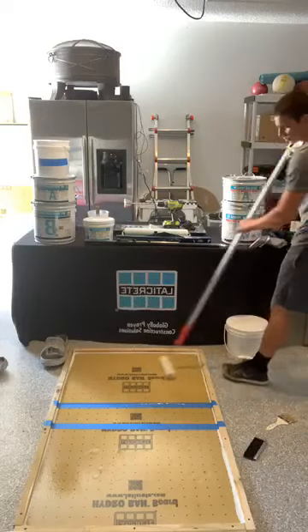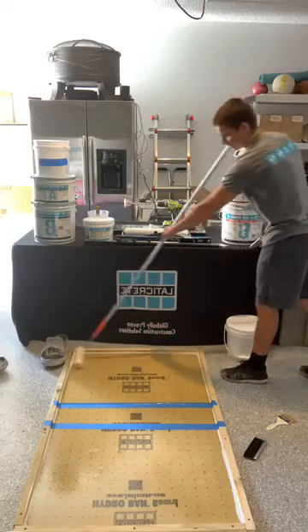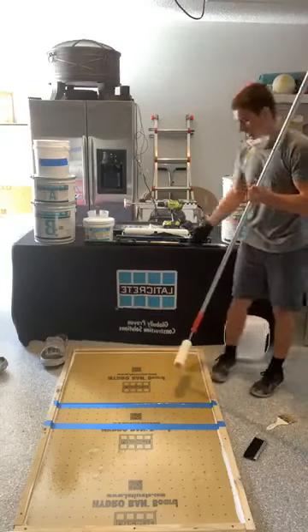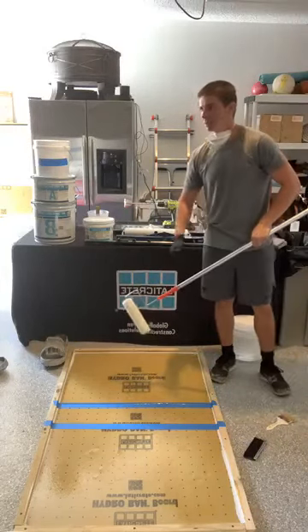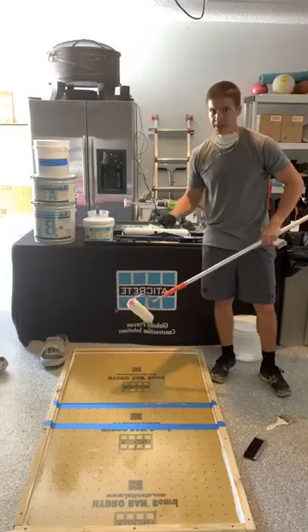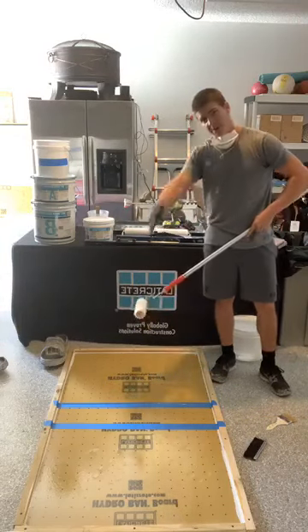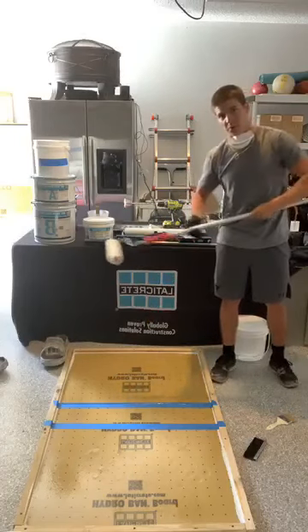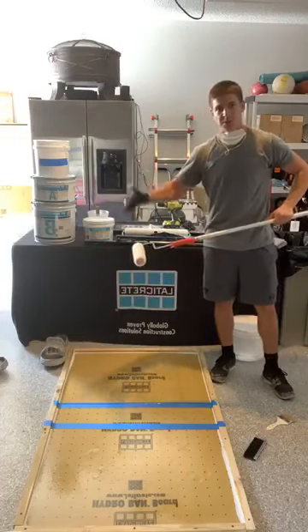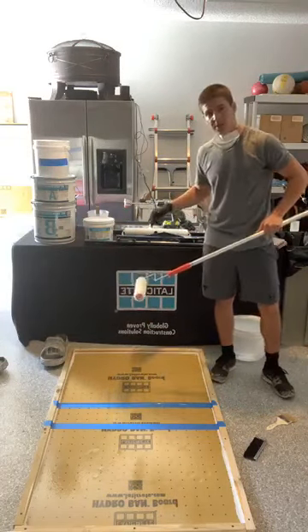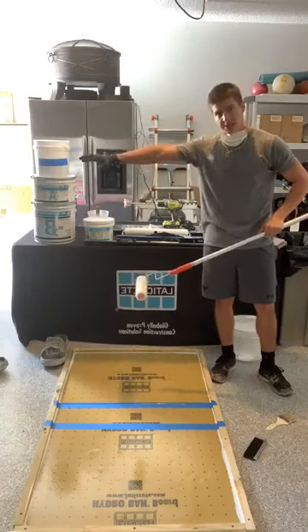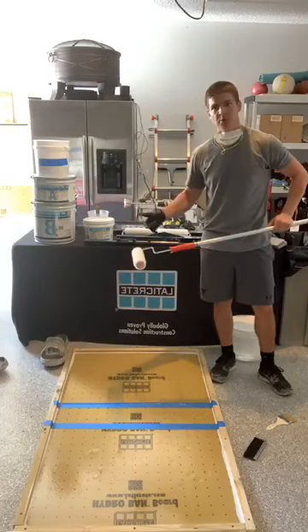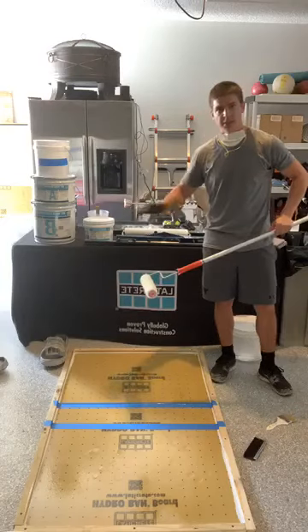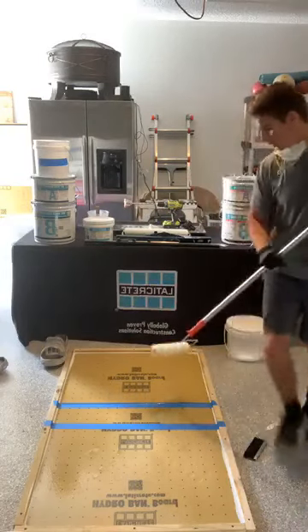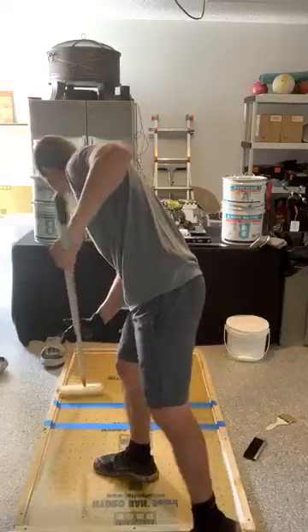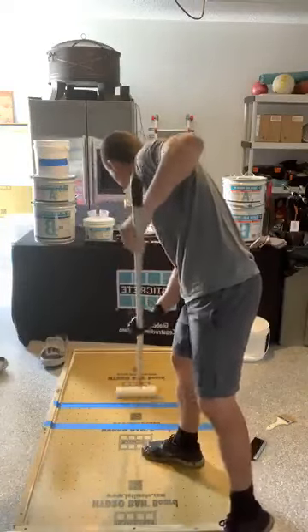Now you would never just roll out epoxy like this on an actual large job, and I'll tell you why. This stuff is about a 200 CPS. It's like molasses. It's very thick. So if I have a ribbon in the middle and I roll away from it, my material is going to want to stay in the middle. So that notch squeegee evenly lays out the material, so that way this roller is not moving product. It's just cleaning up and leaving it uniform. All right, so we'll do a couple adjacent back rolls since I didn't have that notch squeegee.